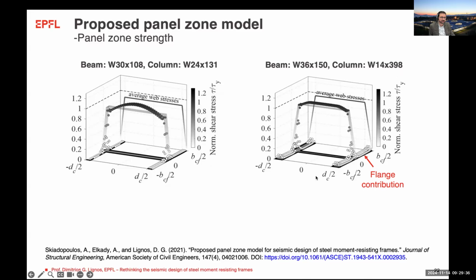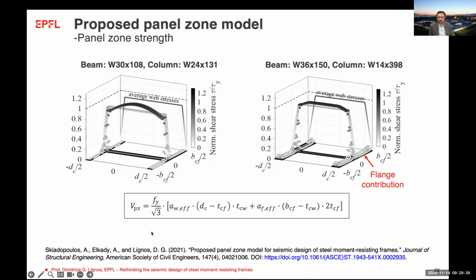So for this reason, we developed a new model that relies on mechanics and essentially captures the contribution of the web as well as the contribution of the flange. And essentially the trick goes into these coefficients, A_w effective and A_flange effective, where with explicit analytical expressions, you can capture the contribution of the web and the flange much more accurately than what's in the literature right now.